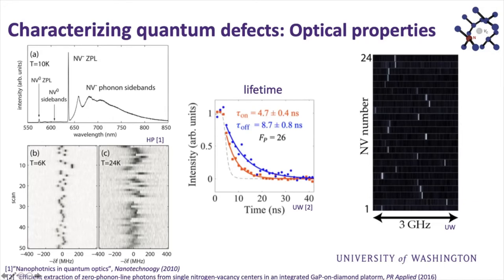So only 3% of the time do you get a photon in this useful transition. But if you zoom in and do very high resolution spectroscopy on this, what you find is that even if you look at a single center, the frequency of that emission may be drifting a little bit. And what's happening there is that just because you're exciting with an optical laser, you're also exciting defects around it, and you're changing the microscopic environment around this defect, which is slightly changing the electric field.